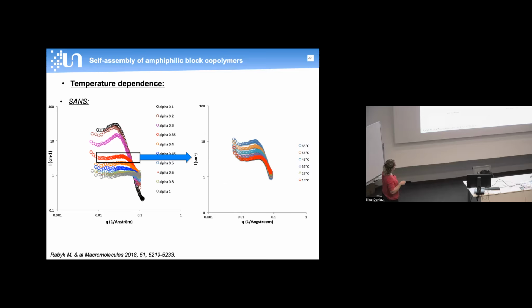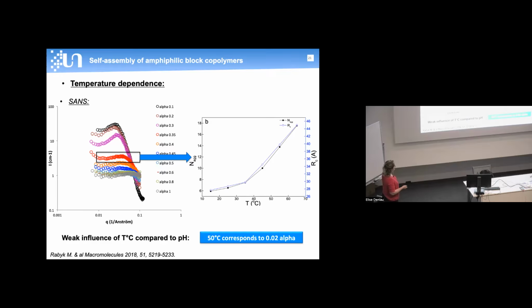So then we took an intermediate alpha in the critical range, which is 35%, and we study the influence of the temperature on the size of the aggregate. And again, by neutron scattering, we could see that by increasing the temperature, the size of the aggregates increases, with an increase of scattering intensity, as well as a shift towards low Q value of the peak of the SANS.